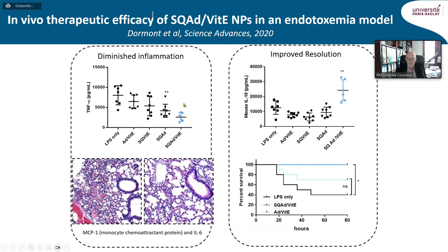You can see that here in blue, after administration of the multi-drug nanoparticles, we had a decrease of TNF-alpha in plasma, which is, of course, a pro-inflammatory cytokine, comparatively to all the other controls, including the administration of a cocktail of the free drugs. And we observed also a decrease of MCP1 and IL-6, which are also pro-inflammatory cytokines, at the level of the inflammatory tissues, including the lungs, where you can see very clearly from the histology that there was a decrease of the inflammatory process comparatively to the untreated animals.